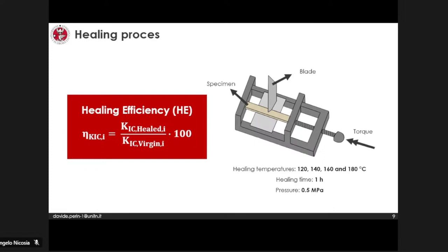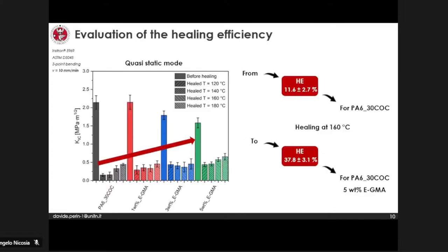So moving to the experimental results, here I reported the K_IC of the quasi-static tests. It is possible to see that by increasing the compatibilizer content and by increasing the healing temperature, the K_IC of the healed specimen tends to increase. If we take as a reference the healing process performed at 160 degrees C, we can see that without the compatibilizer, the healing efficiency was nearly 12%. But thanks to the addition of the compatibilizer, 5%, we increased the healing efficiency up to nearly 38%.